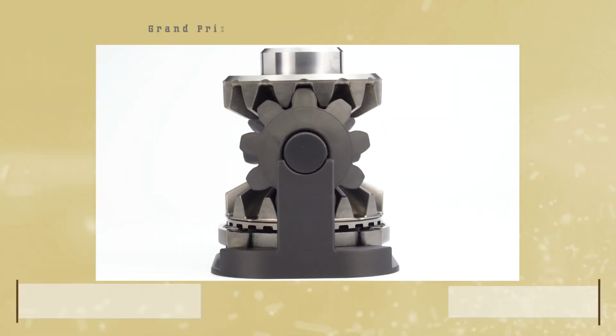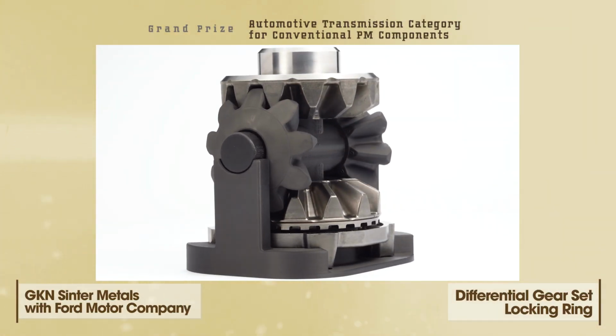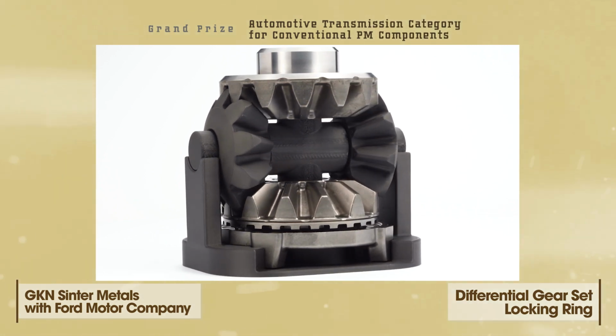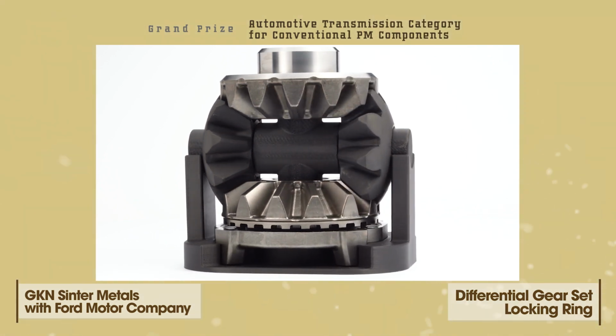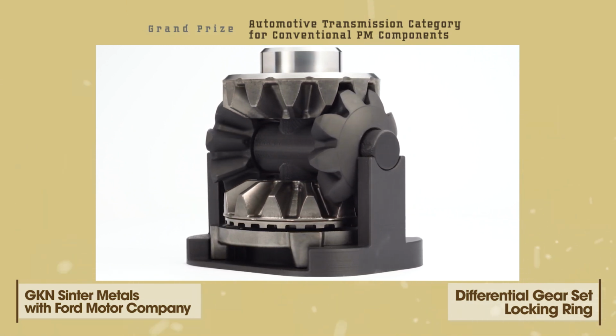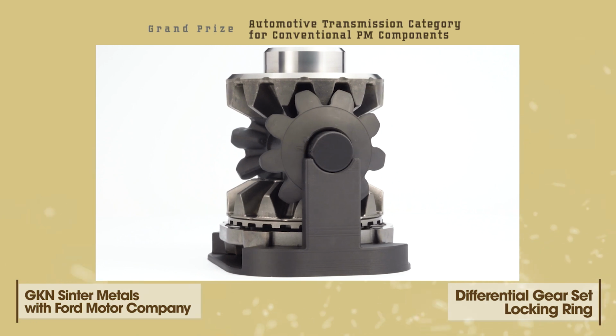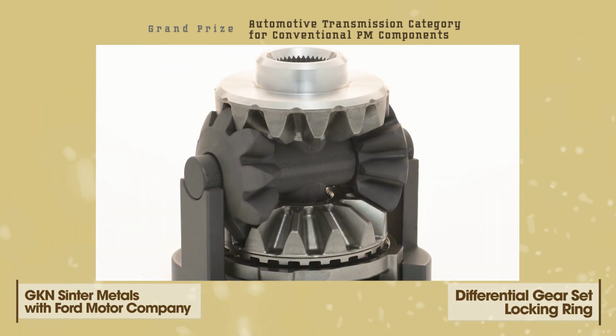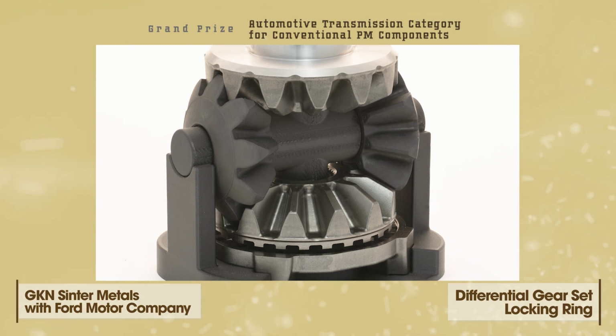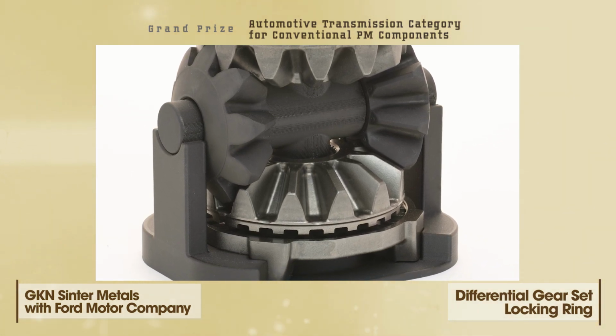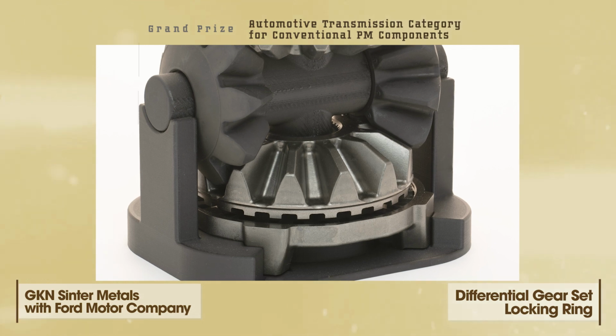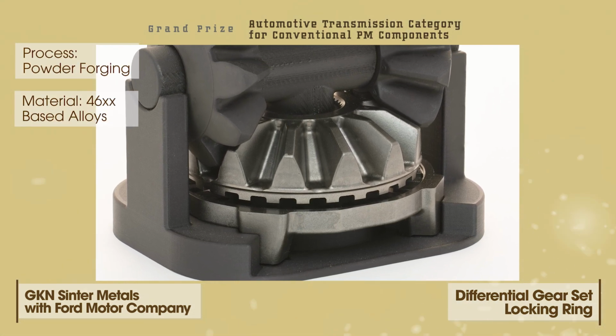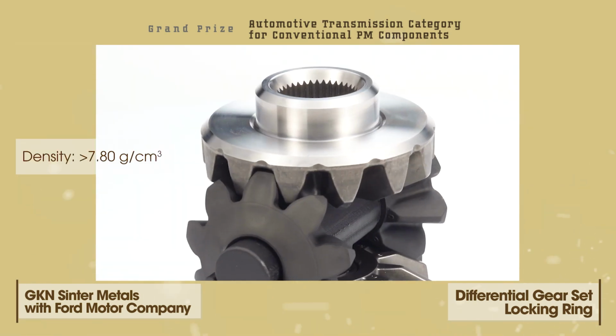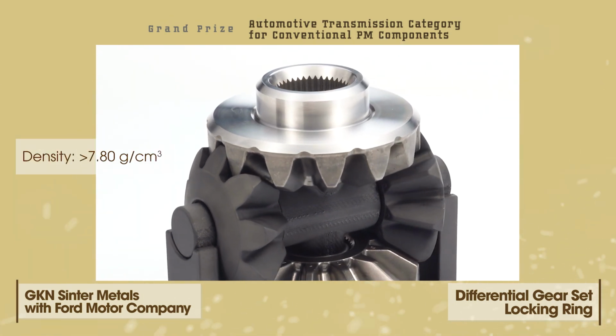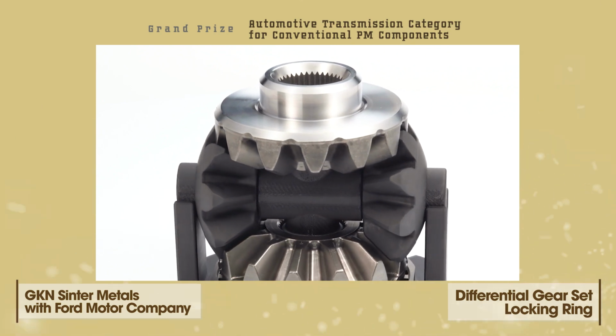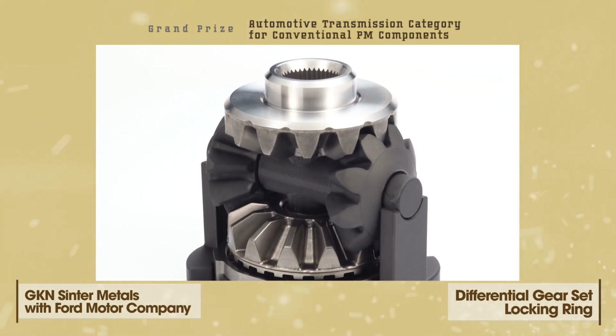GKN Sinter Metals and customer Ford Motor Company received a grand prize in the automotive transmission category for conventional PM components for a differential gear set locking ring. This differential gear set locking ring is used in a rear axle electronic locking differential in 3/4 and 1-ton pickup trucks. The gear set passed full validation for all application tests, including full axle dyno, fatigue, impact, differential seizure, spline interface, and full vehicle durability. The parts, a pinion gear, 2 side gears, and locking plate are compacted, sinter-carburized, net-shape powder forged, quench hardened and tempered, and machined to tight dimensional and surface finish requirements.